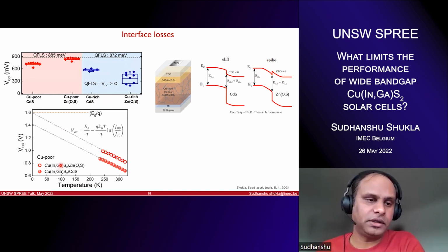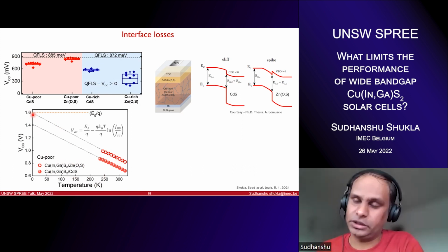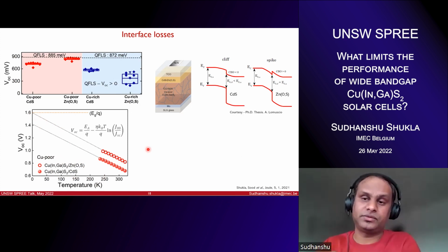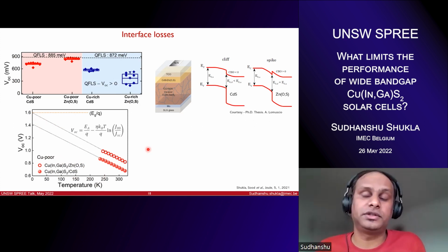And that is what is confirmed from these VOC versus temperature plots. So we extracted the activation energy of recombination from these plots, which is given by this extrapolation at 0 Kelvin. And for the copper-poor absorber with zinc oxysulfide buffer layer, you see this value is close to 1.6 eV, which is equal to the band gap of the absorber. So we cannot say the interface recombination is gone completely, but we can say there is a reduced interface recombination.